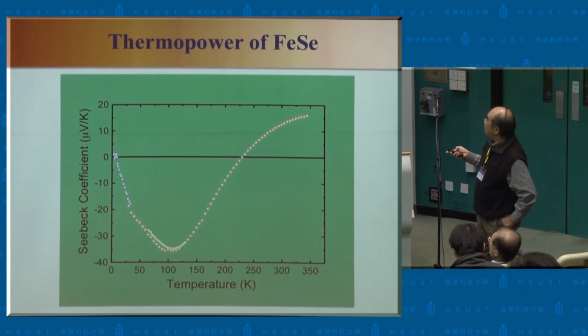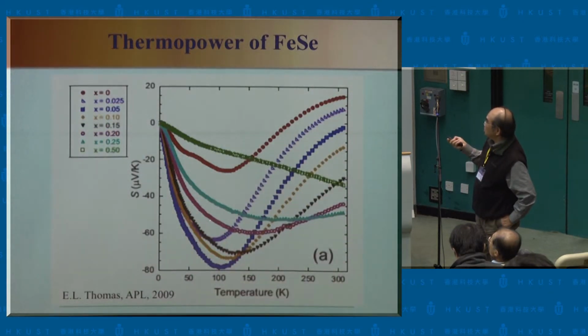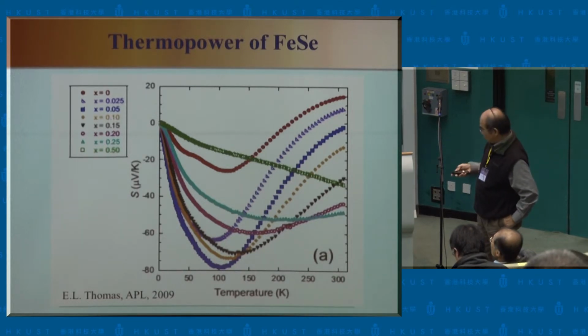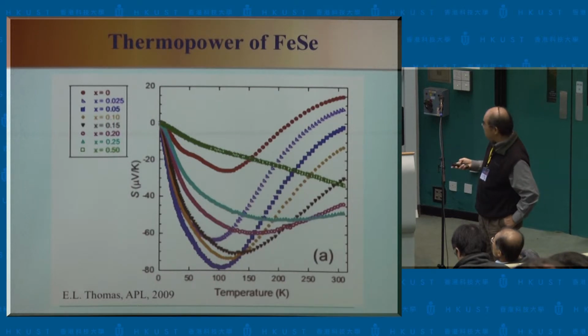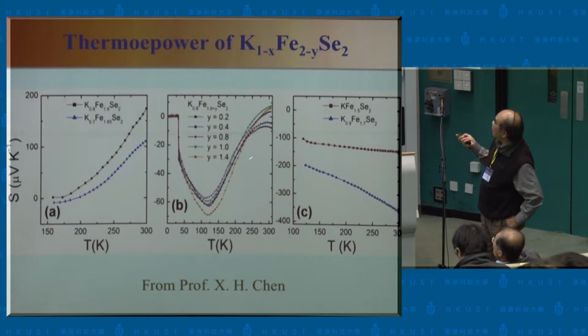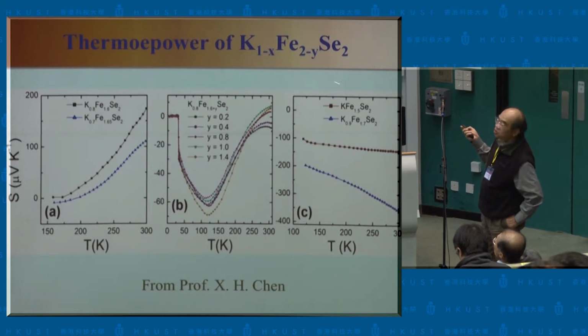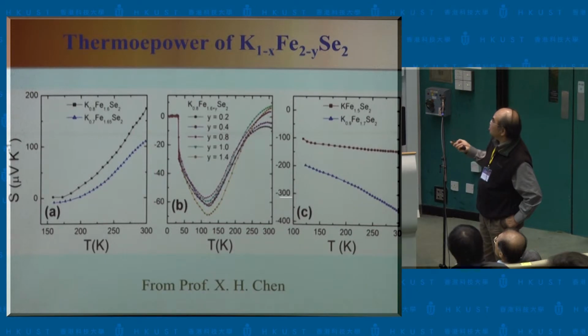Okay? And not only that, you can demonstrate, this is actually by Thomas, they are using copper doping to suppress superconductivity, and when it's non-superconducting, you see there's no such feature. This local maximum gradually disappears, and for the non-superconducting one you don't see it anymore. And this is another comparison for this 1-2-2 system. It's really clear from X. H. Chen's group that in these two non-superconducting regions you don't see any feature, but only those compositions that show a clear superconducting transition have this local maximum, okay? And the value, of course, becomes much smaller.